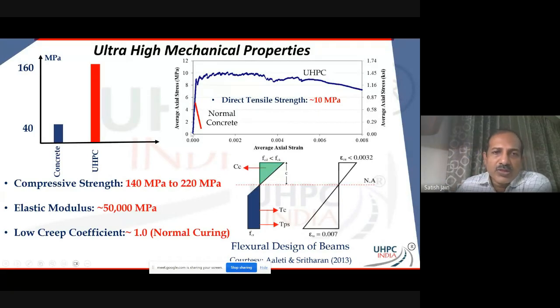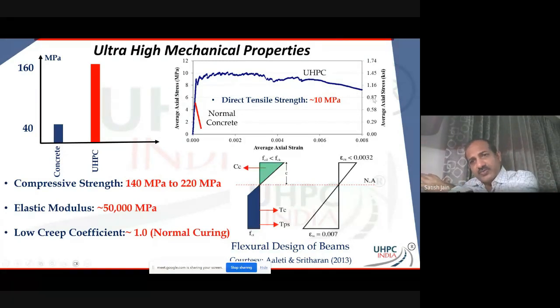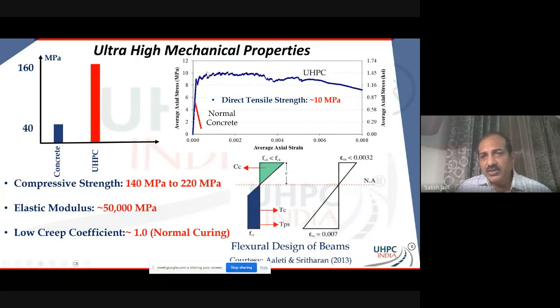So normal concrete will probably go up to 5 or 6 megapascals in tension, and then you'll have a brittle failure. But look at UHPC. UHPC is going to go to 9, 10, even, if you add a little bit more fiber, it can go up to 12, 13 megapascals in tension. But beyond that, you get this ductility, you get this strain hardening, right? And you can go all the way to 0.005 or 0.006 strain before strain softening starts, and it still keeps going. If I were to continue this chart, it'll go up to like 0.015 strain. So this early strain hardening matters.